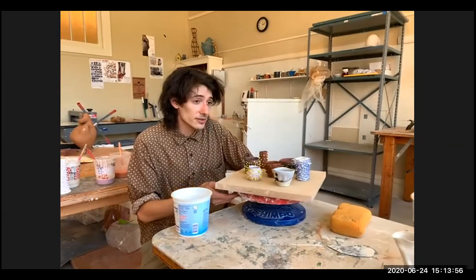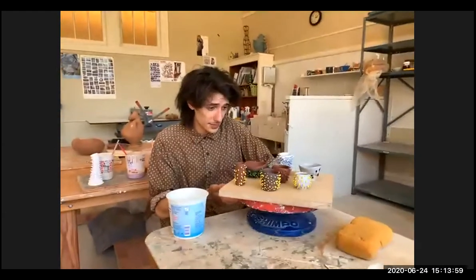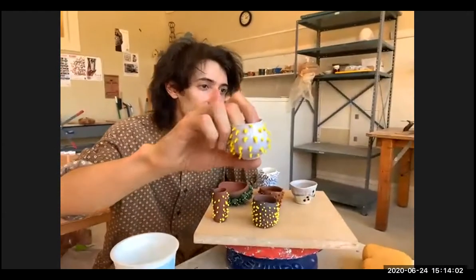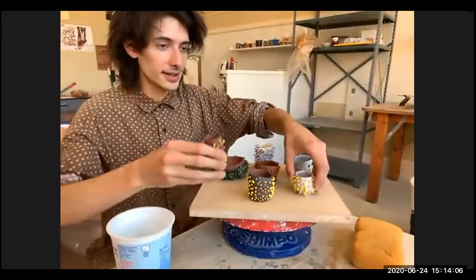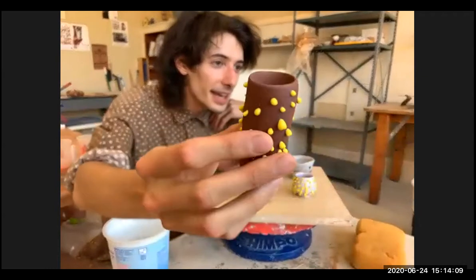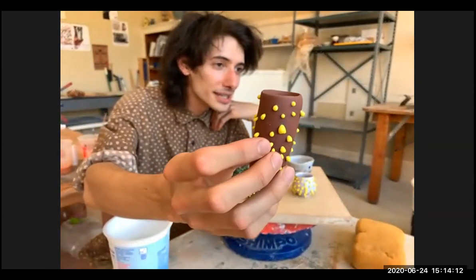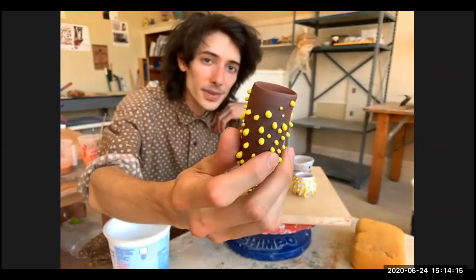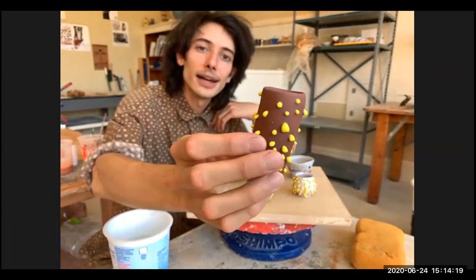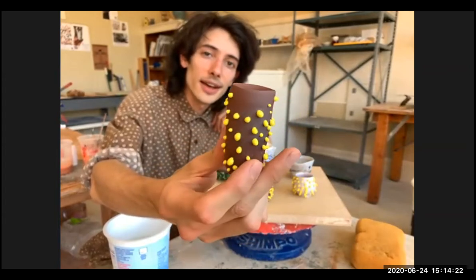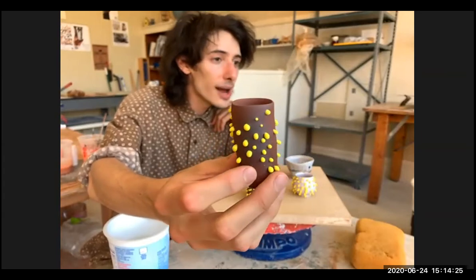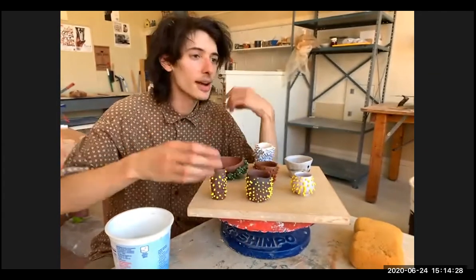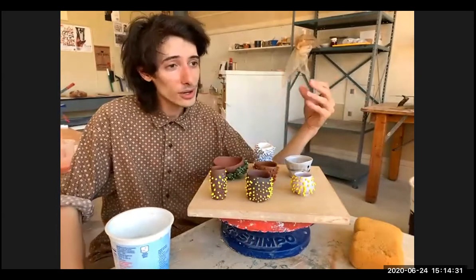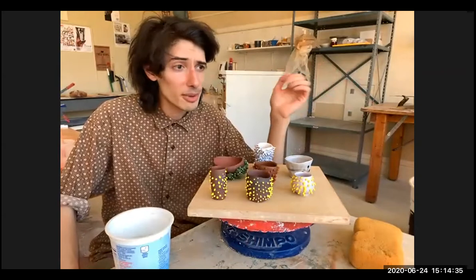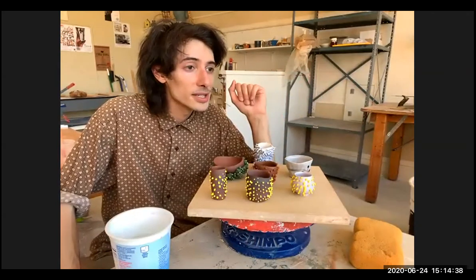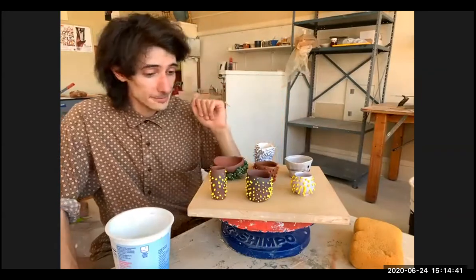I have to admit, I developed these blind, without those maps. I started making things like, well, maybe this is the easiest one. These are little globules that are pretty well melted. They're semi-glossy and they have great surface tension, so they just sit in themselves like little yellow droplets. From there, I did experiments adding silicon carbide. Some of them didn't work. Some were a little too foamy, actually popping and whatnot. So I tried to adjust the recipe with more clay or by changing the firing temperature.